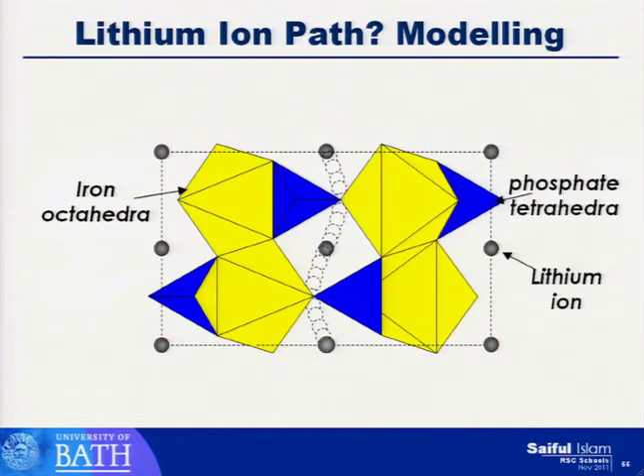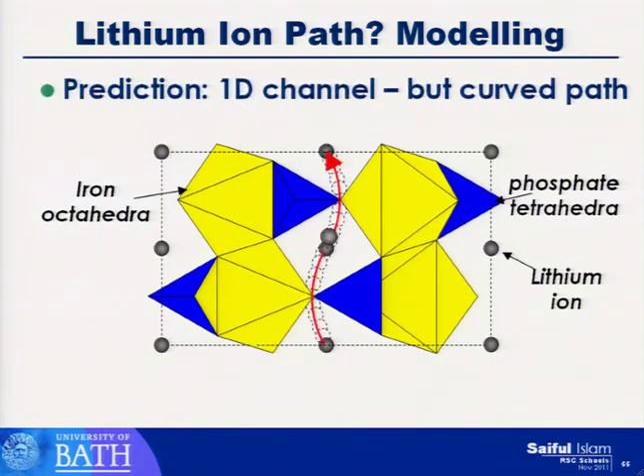But how do the lithium ions move? So this is a slice through the structure. The blue is the phosphate tetrahedra, the yellow are the iron octahedra, and the greys are the lithium ions. And what we find from modeling is that it's not a linear path. Again, the path of least resistance is not straight, it's curved. So we find this prediction that it's a 1D path, but it's curved. We predicted this back in 2005. We thought, again, scratching our head, and basically it's to do with energy. It's like all of us, we want to go along the path of least resistance. It happens to be the lowest energy path.